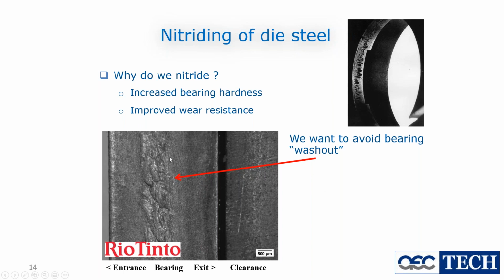So why do we nitride again? We increase the bearing hardness. With increasing the bearing hardness, we decrease the friction and also the adhesive force between the aluminum and the surface. So it improves the wear resistance.